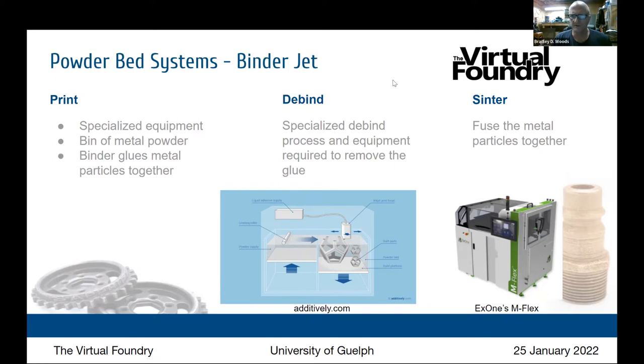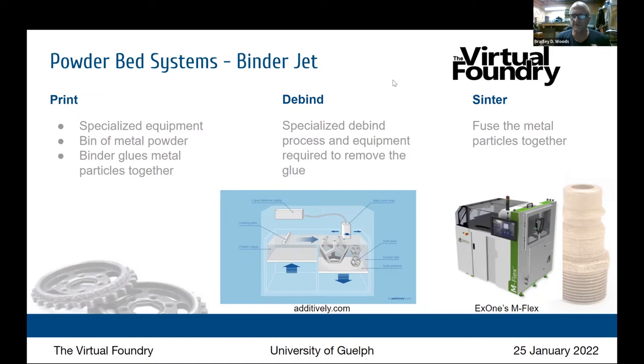After depowdering, the part goes into a large sintering oven. Each metal has different metallurgical requirements. Active materials such as magnesium and aluminum require a shield gas atmosphere inside so no oxygen can be present. Some materials are sintered in a vacuum, others in pure hydrogen — the idea being that hydrogen will devolve any oxygen present by burning it off. A typical sintering cycle for a 12-inch by 12-inch build volume is about two days.